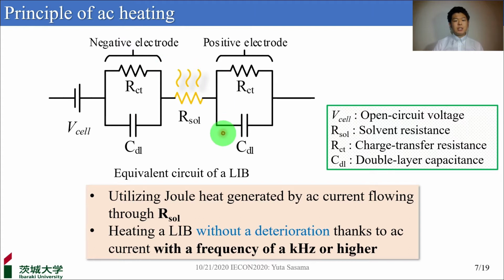This figure shows the equivalent circuit of a lithium-ion battery. A lithium-ion battery charges and discharges by the transfer of electrons between the positive and negative electrodes immersed in the electrolyte solvent. The positive and negative electrodes are represented by an RC parallel circuit, and the electrolyte solvent is represented by a pure resistance. The AC heating technique heats up the battery by utilizing the joule heat generated by AC current flowing through the resistance of the electrolyte solvent.